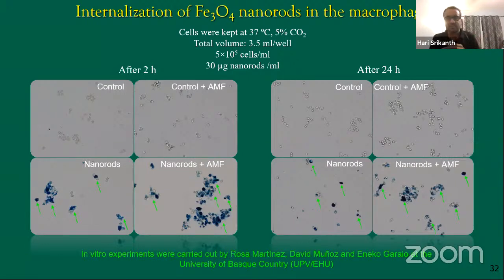So we did toxicity studies by feeding these nanoparticles to different kinds of cells, including cancer cells. So these are macrophages. Macrophages are very hungry. They like to eat whatever they get, okay? And these are nanoparticles that you add to the macrophages, and then after 24 hours, you can see that they're all inside the cells. And then we do the studies, whether the cells can survive alternating fields, current with the particles, without the particles, and that's how we do the study.